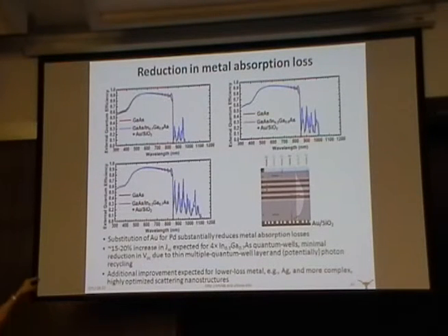You can see that the absorption efficiency has been substantially increased, up to, in this case, a peak that's approaching 70%, in a very small number of quantum wells, and an average over this range of wavelengths that's maybe 25 to 30%.